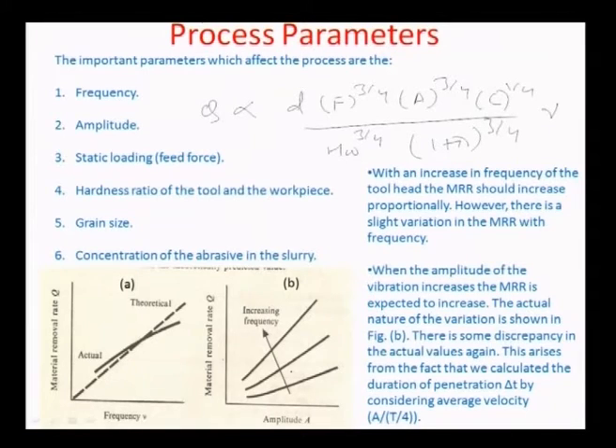For example, as I have already pointed out, with frequency, if the frequency goes high, the material removal rate would go high, so is visible in this particular trend here. Of course, the actual varies slightly from the theoretical, although the theoretical shows almost a direct, linear relationship with increased frequency, but the actual is slightly different because of reasons associated with the inertia of the slurry and also the inertia of the tool head.